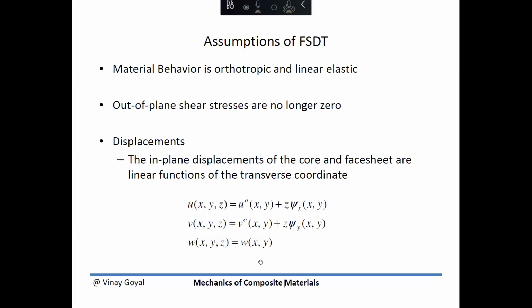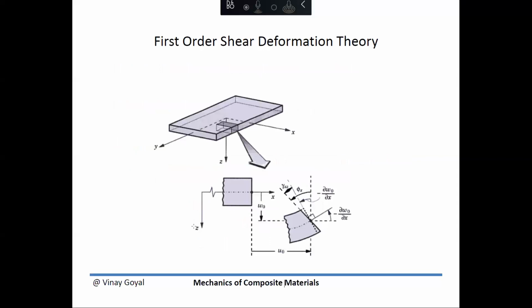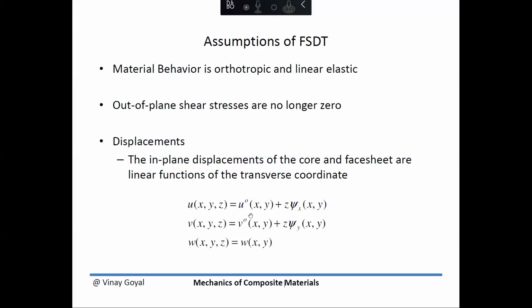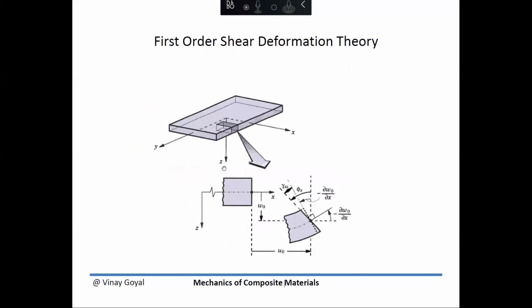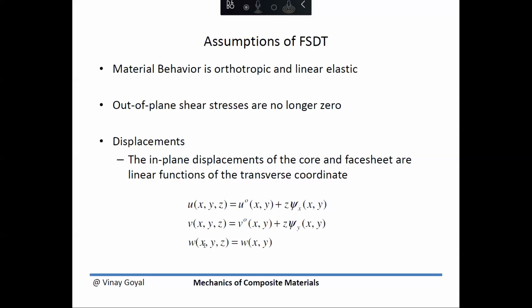And we've been able to accomplish that by making the in-plane deflections U and V, the deflections in the X and the Y direction, a linear function through the thickness direction. You can also see here that W now is the transverse deflection in the Z direction. We're assuming that there's no thickness change, meaning that it doesn't matter where I am through the thickness of the plate, the transverse deflection will be very close to each other, meaning there's no thickness change to that plate.